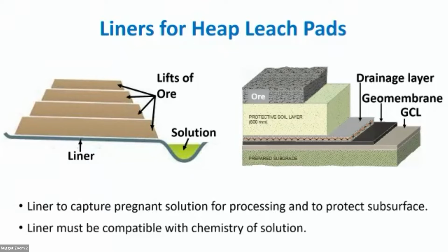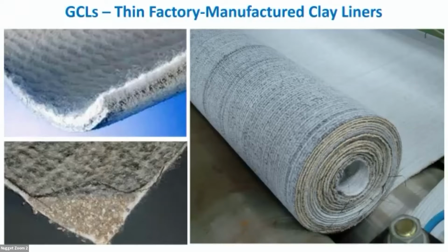And that liner may be constructed out of a geomembrane, a high density polyethylene sheet, a geosynthetic clay liner, or a thin factory manufactured clay liner, or typically a combination thereof, where the two materials work together as a composite to create an extremely low leakage rate, minimizing any loss to groundwater and maximizing our ability to recover the solution. For that to work, though, these materials have to be chemically compatible with the liquid that we're trying to manage. And that really is the essence of these particular materials, these bentonite polymer composites.